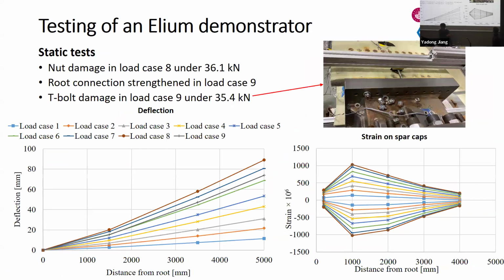In the last load case, we also observed damage of the steel components, which is a tensile failure of the T-bolts, as you can see in this photo. Under extremely high tension, all the T-bolts get tensile failure. If we compare the failure of the nut, which is 36, and the failure of the T-bolt, which is 35, they roughly fail at the same time. So we can see the weakest part of this demonstrator is still the steel part, and we didn't find any composite damage, which is supported by the strain gauge measurements. All the strain values are much lower than the failure strain of the composite material, indicating that the composite material is safe.